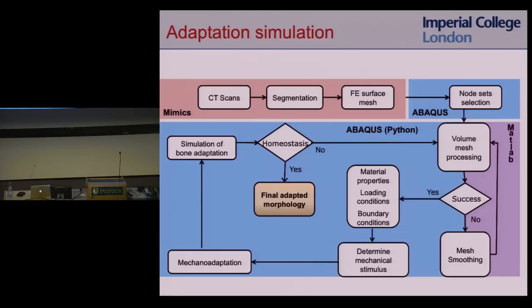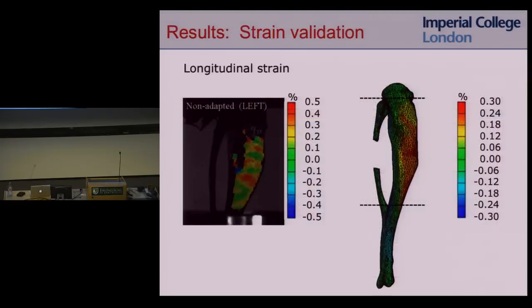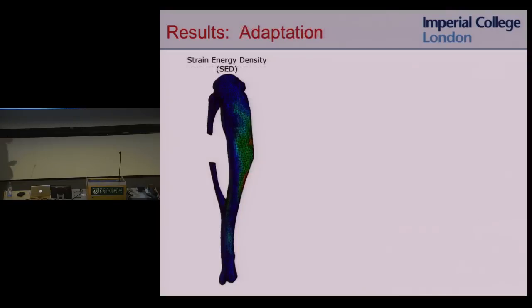So how do we do? The first thing we would need to do is check and make sure our loads match what we see experimentally. So here's experimental. The dotted lines here show this similar region of interest. And you notice that we're slightly off on the magnitude, but we're still in the same order of magnitude. So given our very simplified material properties, it is definitely within the realm of reason. So we're getting tension on this side, and at the other side of the model, we have compression. So the strains check out. We're not too concerned about the difference in magnitude, given all the simplifications we have in our material properties.